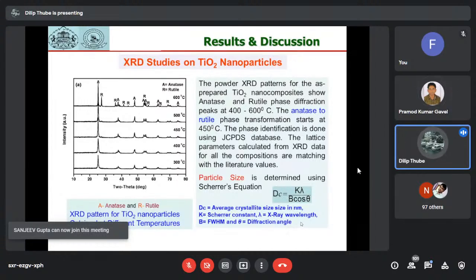If you look at 300, 400, 450 degrees Celsius, there is a slight indication of a rutile phase. And at 600 degrees Celsius, the picture clearly indicates that there is a rutile phase. So at 600 degrees for the pristine material,